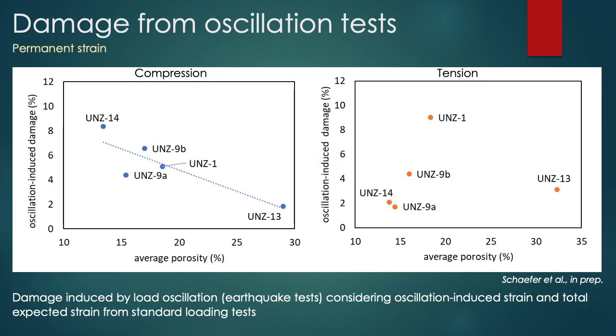In terms of the strain induced in the different materials by the oscillations, we posited that this may be porosity dependent. Here, we compare the increase in absolute strain between the initial and final load-hold portions before and after the simulated earthquake oscillations. In the case of compression, we can see that the more porous samples clearly suffer less permanent strain, suggesting that they may buffer the earthquakes more effectively.